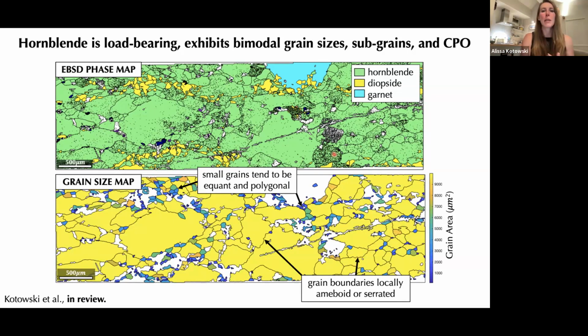So with this EBSD phase map on the top, this is just color-coded by type of mineral. All of the green here is this hornblende amphibole. And you can see that it's actually creating the majority of the framework of this microstructure. So we can use this observation to say that the hornblende is controlling the strength of the rock at this scale. We also see that there is a bimodal grain size distribution.